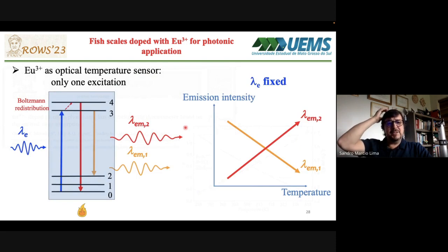So, as usually is done when we are investigating optical sensors of temperature, we looked for optical materials with some technical advantages to make the developed system available commercially. So with this interest, we performed a test with another configuration in which only one excitation pump is enough to control the temperature of the device. The idea is to pump the electron here from level zero to level three. And we observe the photoluminescence from level three to two by increasing the temperature.